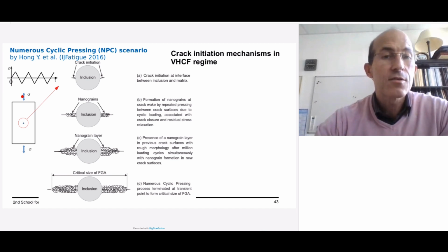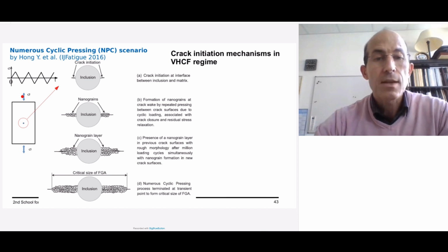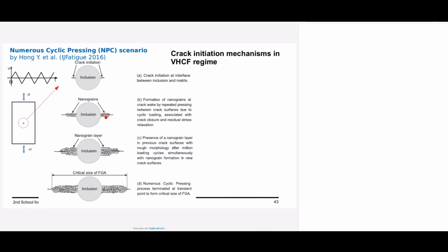So when there is a part of the cyclic loading under compression, after the initiation of the crack by debonding around the inclusion, there is refinement of the grain, like in the Sakai scenario. And so the nanograin formation increases because of the pressing of the external cyclic loading, and the increase in nanograins will finally create a micro crack which is open. The growing of these open micro cracks will lead to failure, and the size of the fine granular area or the optical dark area corresponds to the size of the region where there is nanocrystallization, recrystallization.